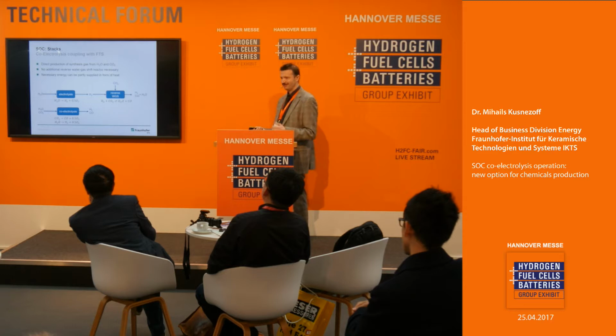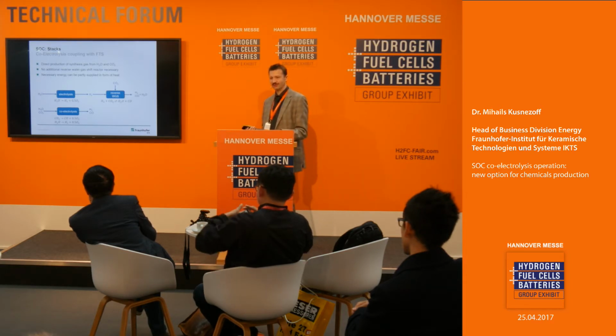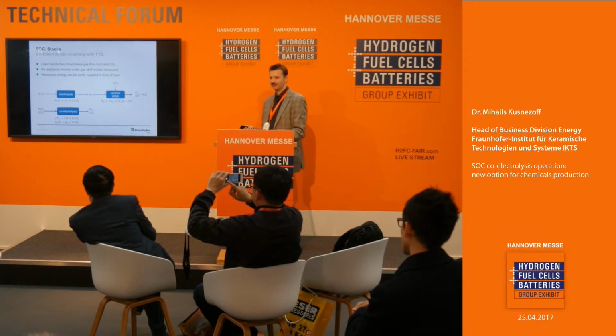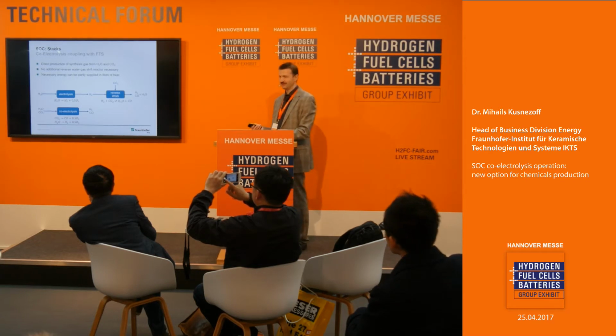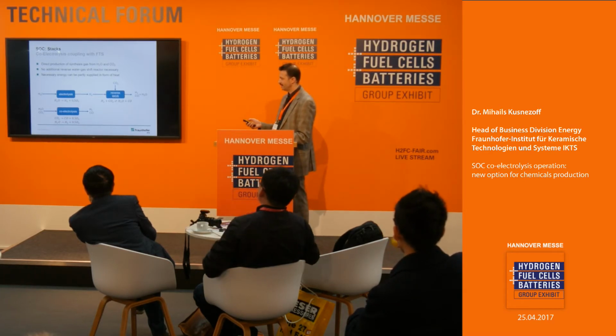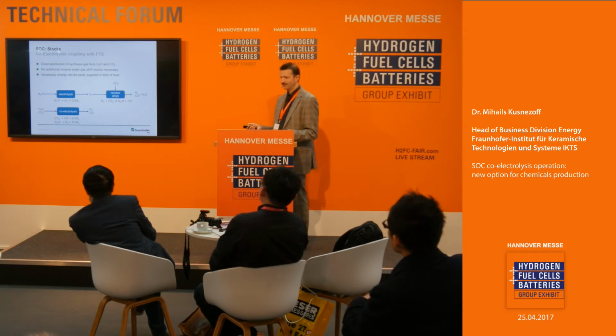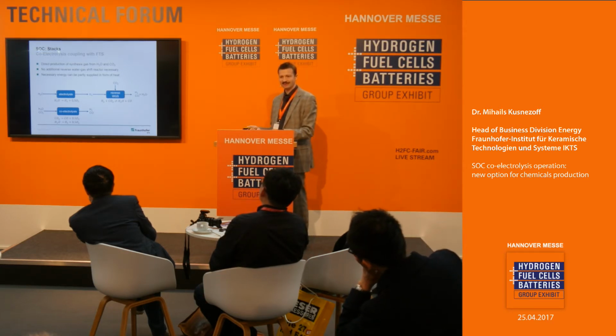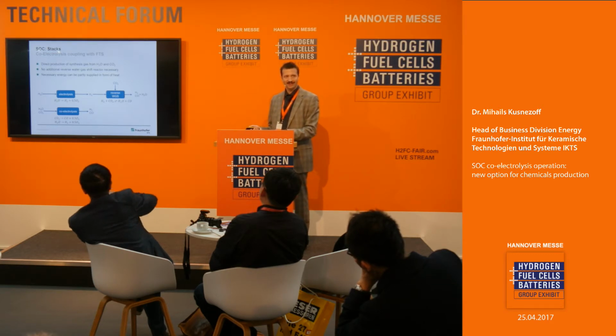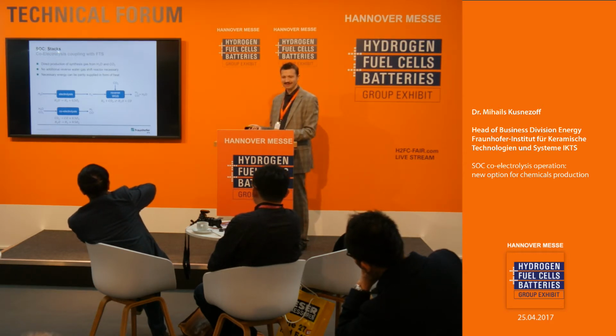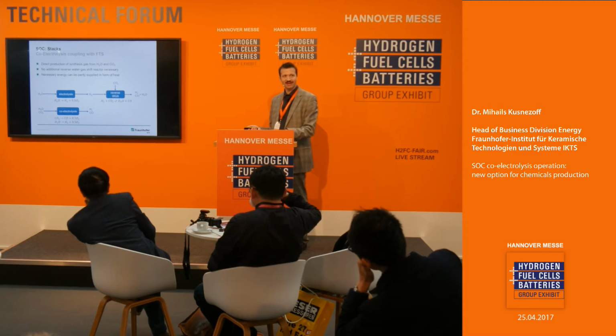Now about the future. So we think that this option for providing direct conversion of a mixture of steam and CO2 is very interesting for combination with Fischer-Tropsch synthesis. Because in this case, we have only one reactor which converts both components and also adjusts the stoichiometry. And in this case, we can use temperature as an equilibration factor to adjust stoichiometry between hydrogen and CO, which is needed for chemical synthesis.